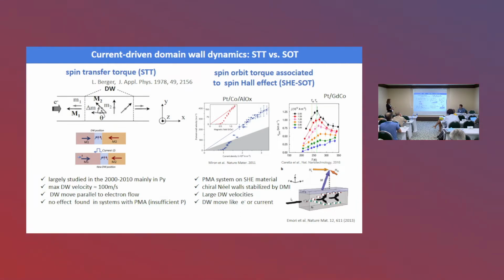But as you probably all know, in the last 10 years or so we have concentrated on samples in which cobalt or ferromagnetic layers are deposited on heavy metals, so we have a spin-orbit torque that moves domain walls that are stabilized with a certain chirality by Dzyaloshinskii-Moriya interaction. Matthias has just talked about that. In that case, the larger velocities are obtained in ferrimagnetic systems close to the angular compensation. And domain walls can move either in the direction of the electron flow or in the direction of the current, because this direction depends on two interactions: the sign of the DMI, so the chirality of domain walls, and the sign of the spin Hall angle, so depending on platinum or tungsten as the heavy metal.